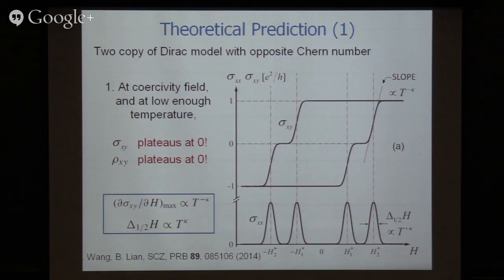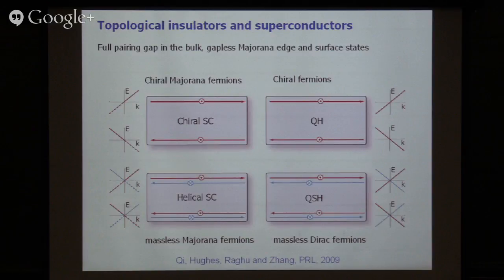A Princeton group claims to have seen some basic signatures of this. And when you analyze these peaks, this is a textbook quantum critical phase transition, and the width of these plateaus, the width of this peak, and the plateau transition should all obey some universal scaling laws, which should be the same as those of the quantum Hall effect. They give you another model system to study.